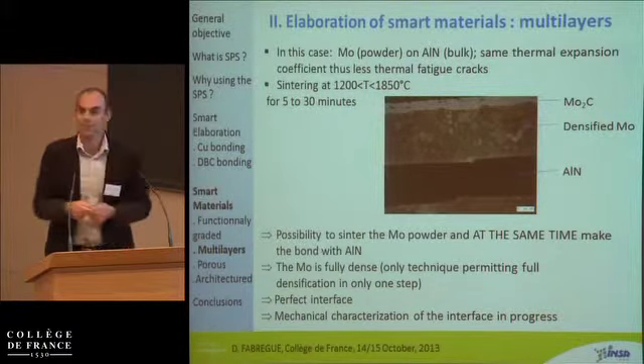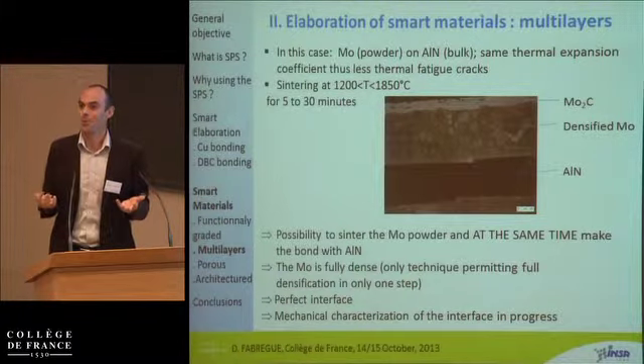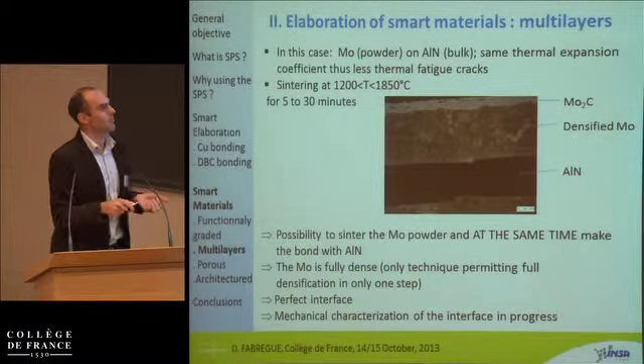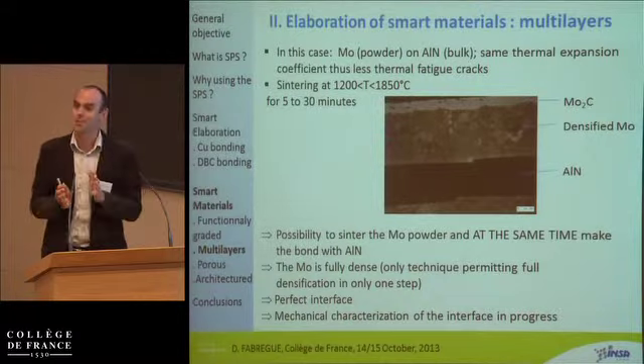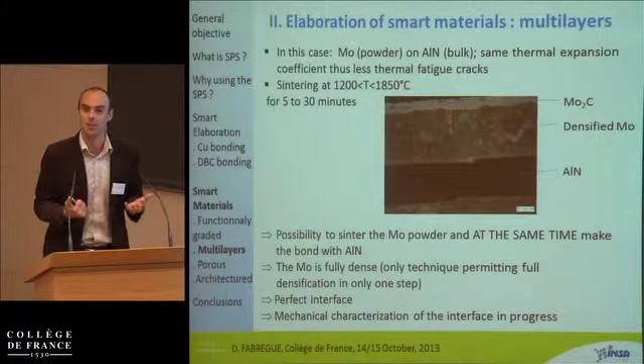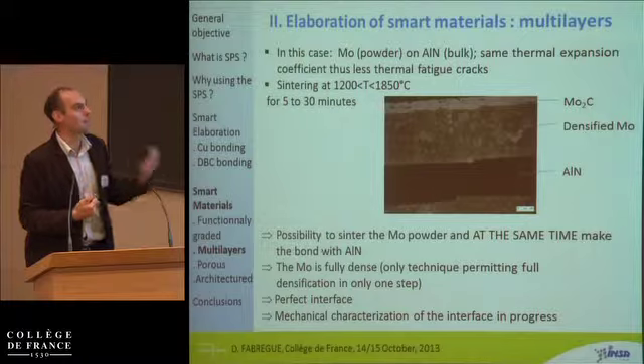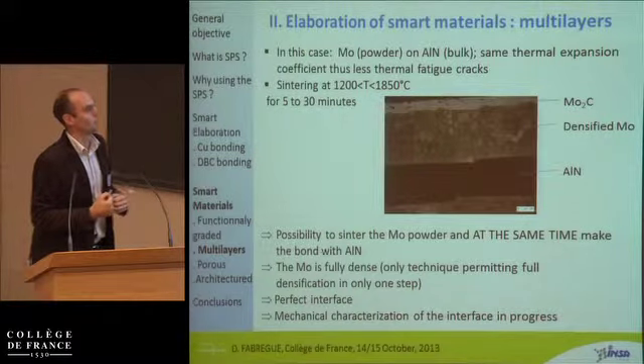And now we are doing the same thing, but co-sintering the two of them. We put aluminum nitride powders and molybdenum powders, and we co-sinter the two of them in order to get a diffuse interface. We succeeded in that, and now we are trying to measure the mechanical properties of this type of thing.